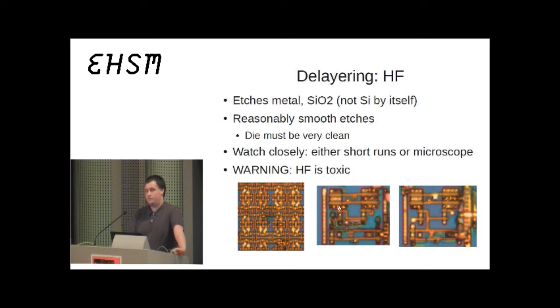One of the other things too is because you are etching down, you have to watch it very closely. It is very easy to let it sit for a little while and have it go too far. So for example, these polysilicon, which is maybe what I'd want in this photo, if you let it sit for a little bit longer, it would etch the silicon dioxide under it. And although it won't technically destroy the polysilicon, you will actually see it float away in the solution and ruin your images.